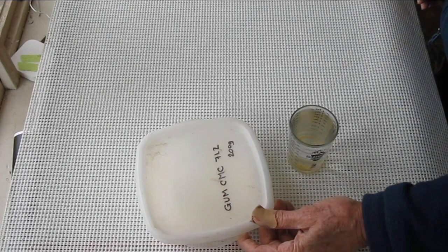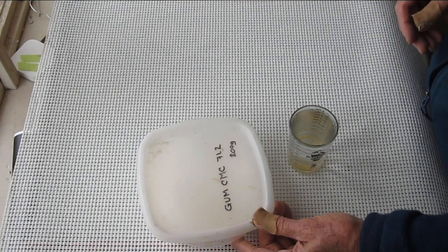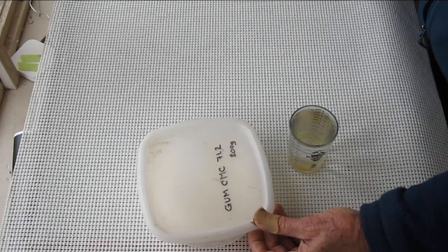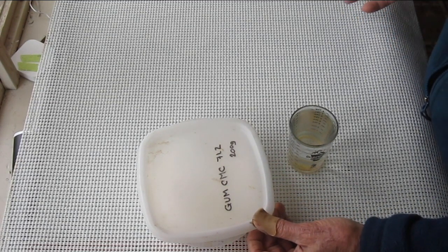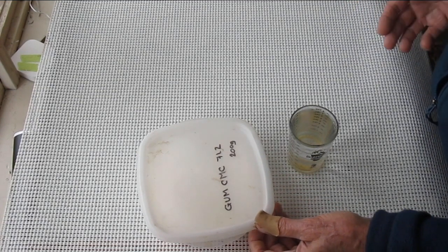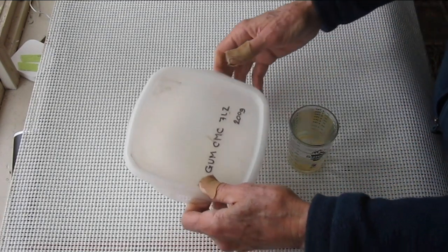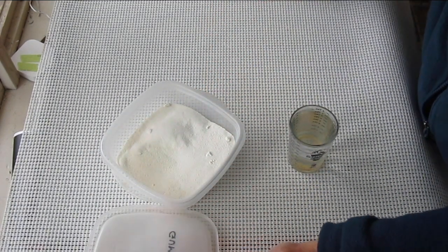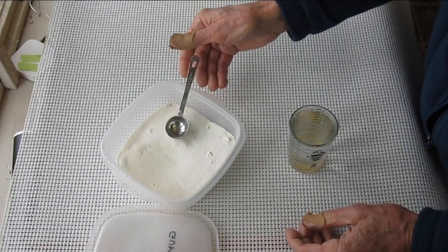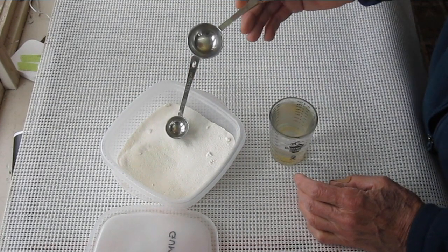Now, the first thing one has to do is to make a solution of gum to put onto the paper, which will turn ordinary paper into a pseudo water slide paper. Water slide paper is what the industry calls their basic decal paper. And what you do is you start with some CMC gum. I put in a teaspoon into about 10 tablespoons of water,